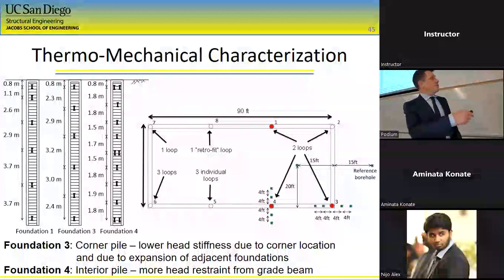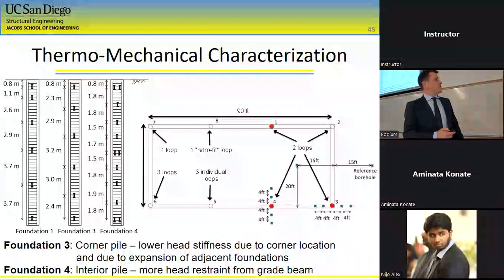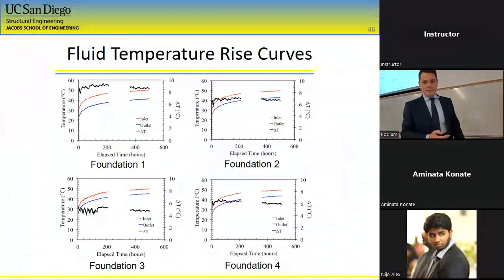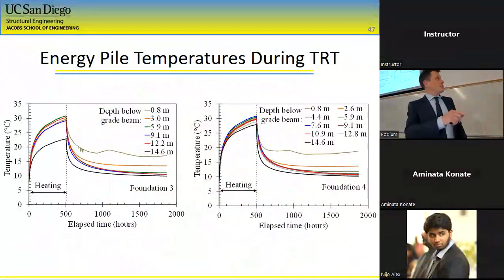So then these are the 3 piles that had a lot of strain gauges on them, so I'll focus on those. Each one of them was a little bit different: a corner pile, an interior pile, etc. So we did a heating response test for each of those, had a constant heat input rate and watched the temperature rise. And during that process, the pile temperature increased, and then we shut it off and it cooled off.